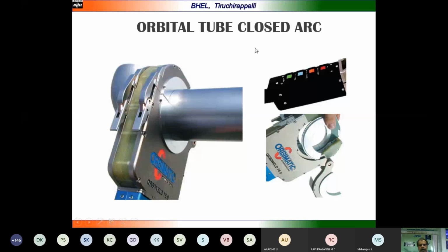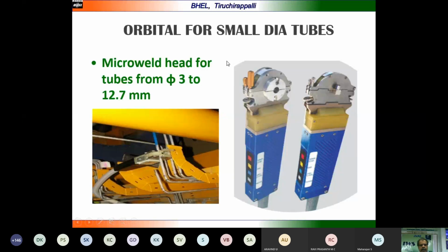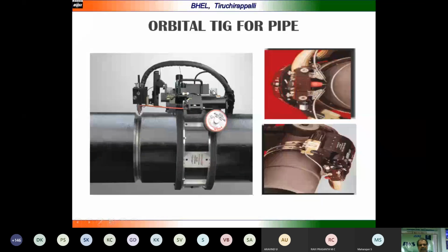Smaller diameter tubes, 3 mm to 12.7 mm, can also be welded using this process. This is orbital TIG welding for pipes. What we are seeing here is similar to tubes, but the pipe can be a bigger size, and the head can move over the ring, and the welding can be done in many subsequent passes.